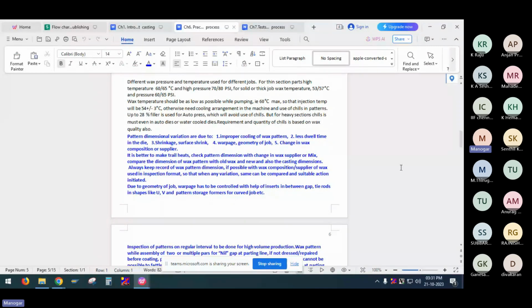Change in wax composition is an important point in the investment casting process, because when you change the wax, either supplier or batch, then we have to first check the stability of the wax, or the dimensions we get from the same wax, whether the repeatability is there or not from the previous batch to the next batch. It's always better to check the first pattern from the new batch and confirm the dimensions. So it is better to make a trial, and check the pattern dimension and also the cast dimension. In some cases this happens: the wax dimension is okay, but in casting it varies because of the wax composition.